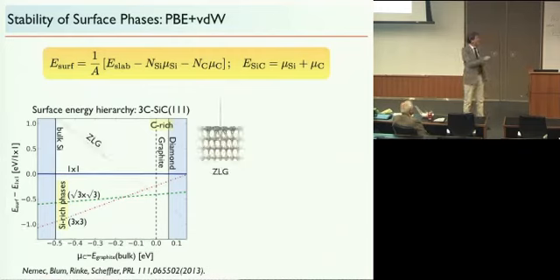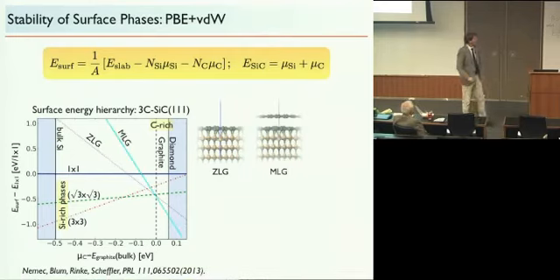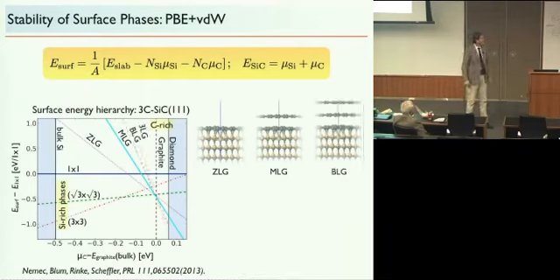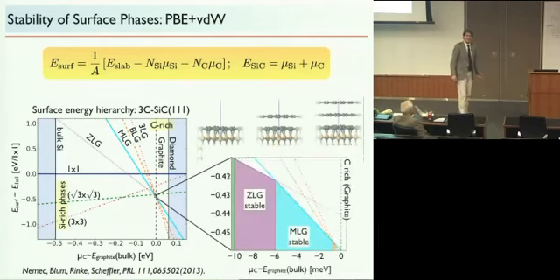And if we draw in our zero-layer graphene structure, we find that in a very narrow range over here, it actually crosses and becomes the lowest energy structure. If we go closer to the graphite limit, monolayer graphene also becomes stable, and bilayer, trilayer we can also draw into this. So if we zoom this out, we get a very narrow range where either zero-layer graphene or monolayer graphene is stable. Now this is in agreement with the experiment, that there is a phase area where you can grow this as this thermodynamically stable phase. For monolayer graphene, we also find such a phase.